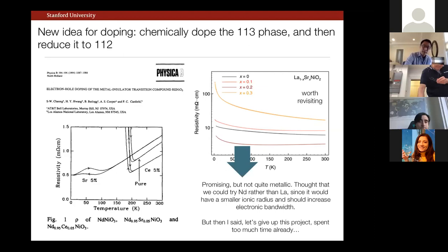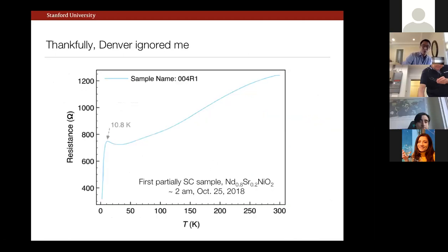But also, to be fair to history, I had said to Denver, hey, we've already spent so much time unproductively on this project, let's give up. And of course, another important piece of good fortune here is that he ignored me, as should have been the case. In fact, here I show you directly a trace of his first partially superconducting sample. Like most things, that only seems to occur in the middle of the night. You can see here this resistivity scale does not go to 0. So it's only a partial transition down to 2 Kelvin where we measured. But this was the first step in seeing something interesting.